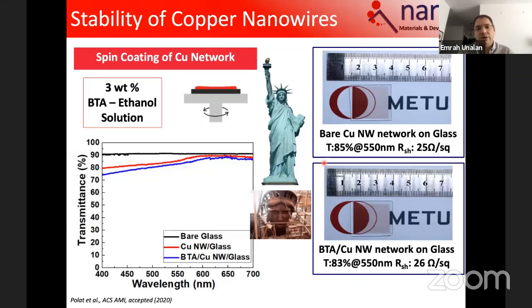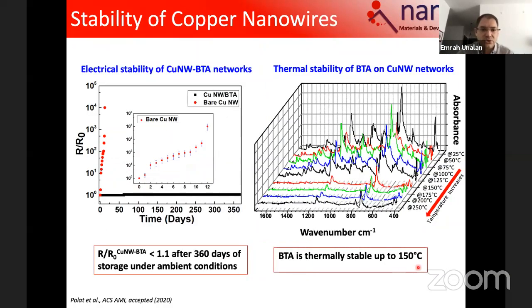Okay, so our solutions for the stability are twofold. One of them is an organic solution, and the other one is an inorganic solution. So once we were doing a patent search in literature, we came up with benzotriazole, which was used for the corrosion protection of bulk copper. And the idea immediately came into play. Why don't we use this BTA on top of the nanowire networks? We just mix it with ethanol, and we spin coated it. The transmittance, as you see over here, is not changing at all. It's just a slight variation, and the sheet resistance is not drastically changing either after the BTA deposition.